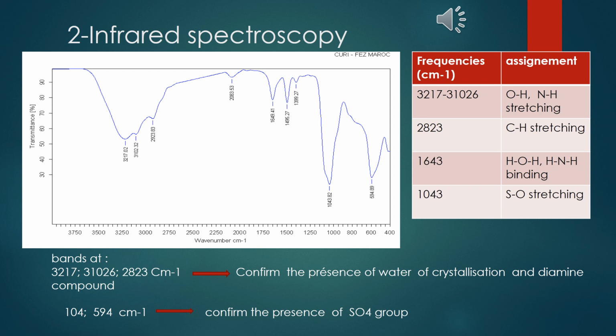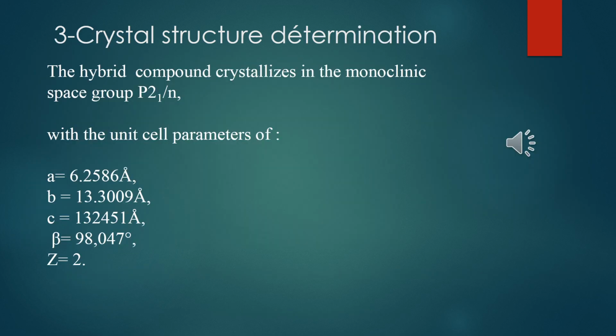In order to establish the crystal structure of this compound, infrared analysis was made. It shows the bands that confirm the presence of water of crystallization, trans-diaminocyclohexane, and sulfate groups. The characterization by X-ray diffraction shows that this hybrid compound crystallizes in the monoclinic system with the following parameters.